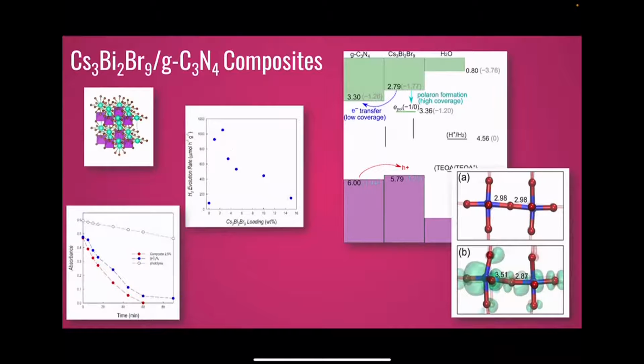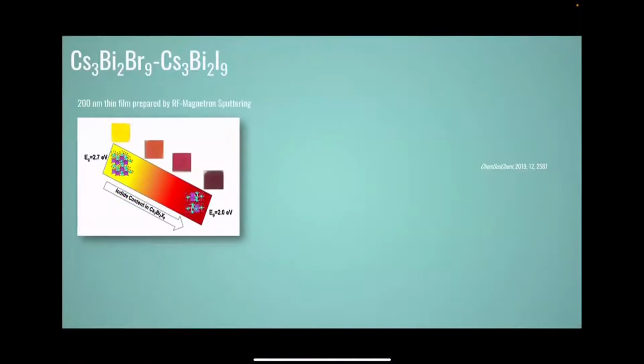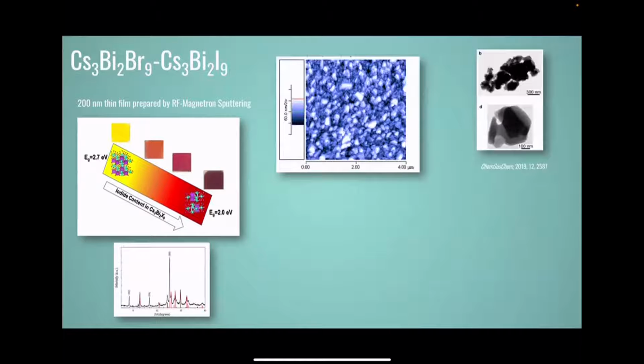Of course, starting from powders, we move to thin films. We prepare these thin films by magnetron sputtering, so vapor phase deposition. You see, you move the band gap from yellow to red if you move from bromide to iodide. The films are very good films. Okay, diffraction patterns. This is the morphology.